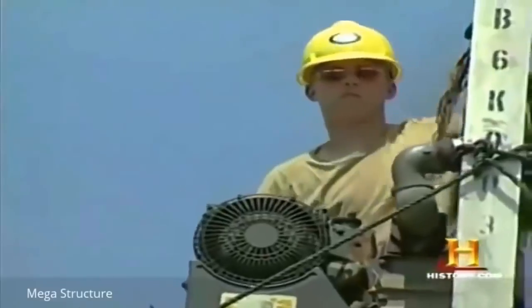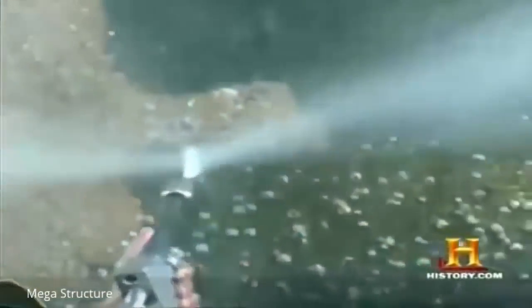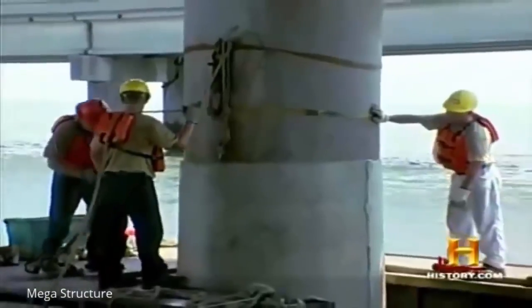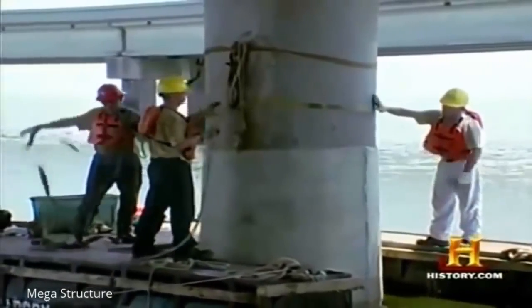One crew will clean the marine growth off of the piling, using anywhere from 6,000 to 10,000 psi water blasting above and below water. The second crew, the way we've got it worked, sets a 1/8 inch thick fiberglass jacket that stays in place. And then the third crew basically comes behind them and pumps an underwater epoxy grout into the fiberglass form that stays there.